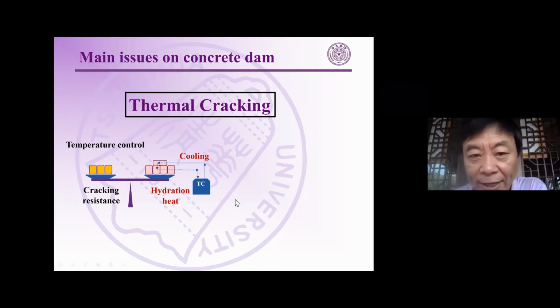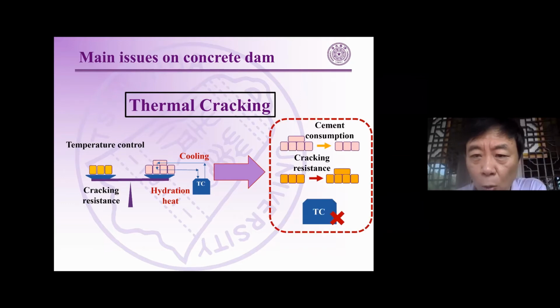Like this, you have to embed some cooling pipe in the concrete and let cooling water run through the cooling pipe to let the hydration heat dissipate from the massive concrete itself. And this cooling pipe temperature control is very complex. So usually we want to reduce the risk of thermal cracking by lowering the cement consumption.